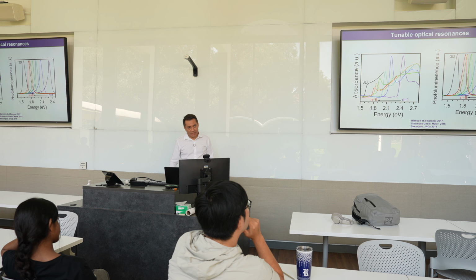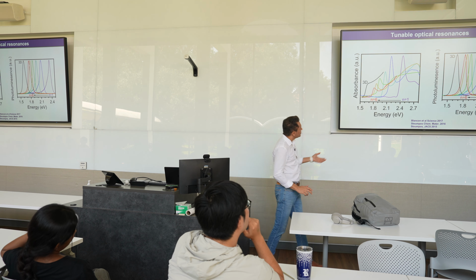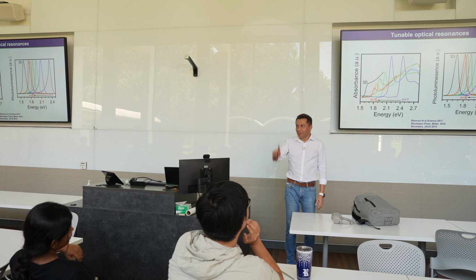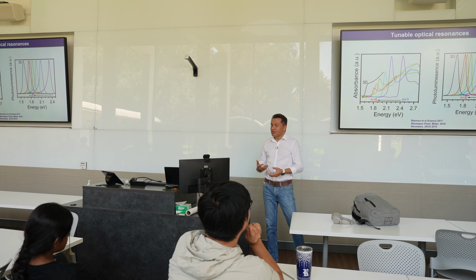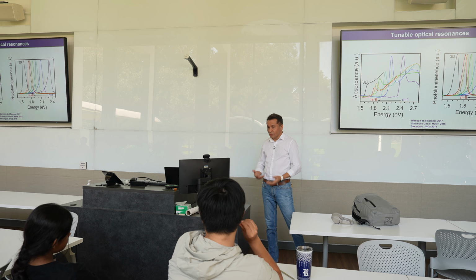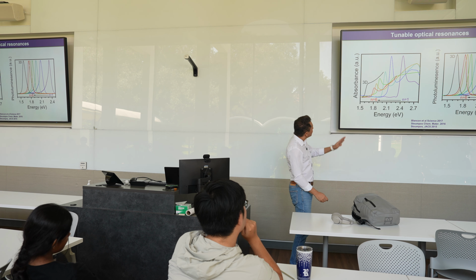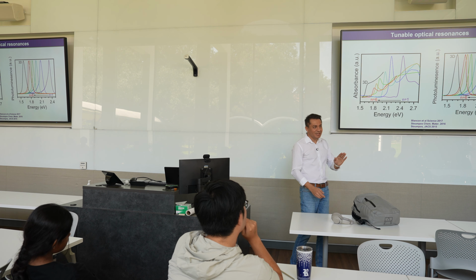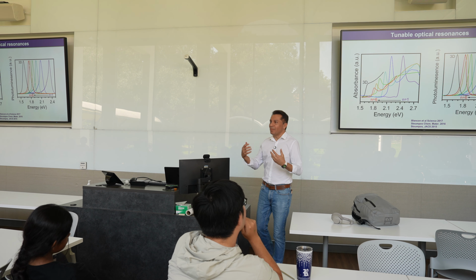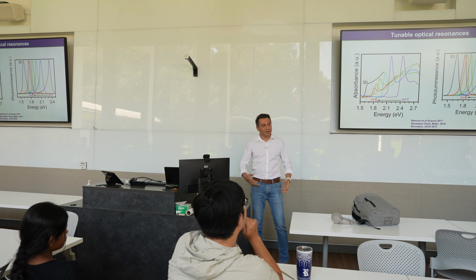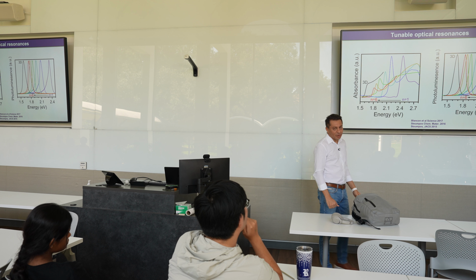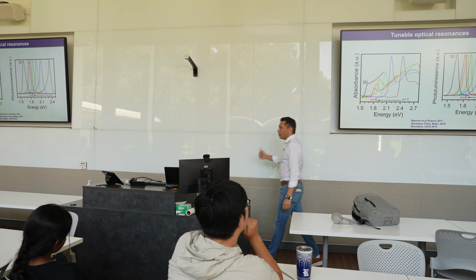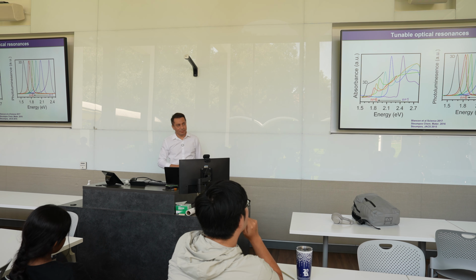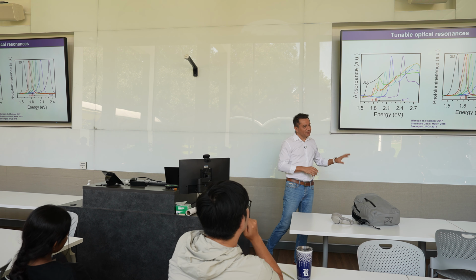In fact, this is what you see. On the left, you have absorbance. As you go from N1, you see a sharp resonance. The dominant resonances in these materials are excitons, right? And as you move to N6, you can see that this excitonic resonance starts to get weaker and weaker. Your binding energy of the exciton gets weaker and weaker. You are decreasing your quantum confinement, right? And in the corresponding photoluminescence, you can tune this very beautifully, okay? So I won't talk so much about this, but I wanted to give you a flavor of these materials.